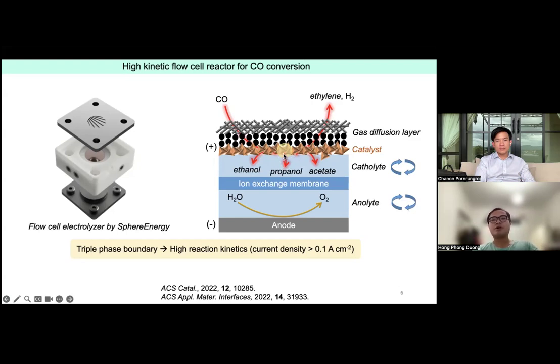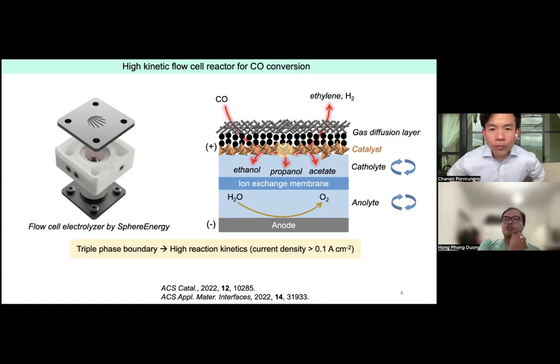Okay, the important thing here is that with the gas diffusion layer, we can also achieve a thing called triple phase boundary. So what is it? Triple phase boundary means the phase between the catalyst, the input gas, and also the electrolyte. And since we make this boundary, we can run the reactions at very high kinetics, and usually these cells allow us to go up to ampere-level current density, which is very demanded for industrial applications, because in industry we want a very large amount of product in a very short time. So it means you need a very high kinetics, and you also need to reduce the resistance of the electrolyzer.